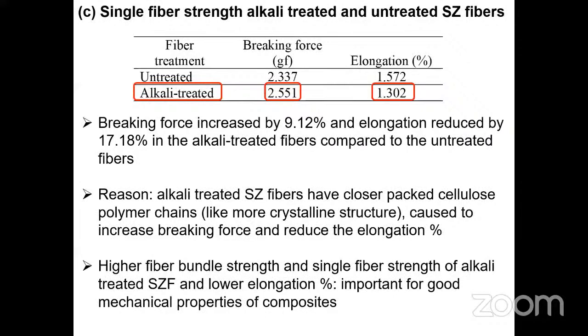In this slide, you can see the single fiber strength of treated and untreated Sansevieria zeylanica fibers. As per the table, the breaking force increased by 9.12 and elongation reduced by 17.18 in the alkali treated fibers compared to the untreated fibers.